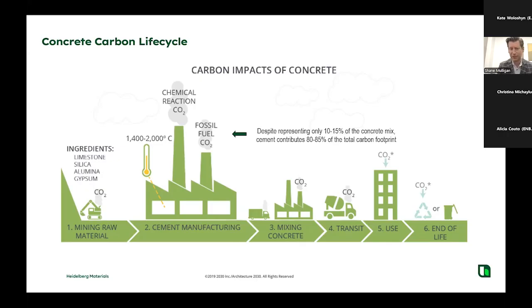Then you have the cement manufacturing process itself. And that really is the elephant in the room when it comes to the carbon footprint of concrete. Despite representing only 10 to 15% of the concrete mix, cement contributes somewhere in the range of 80 to 85% of the total carbon intensity of that concrete. So it is definitely the main contributor to why concrete is considered a carbon intensive material.